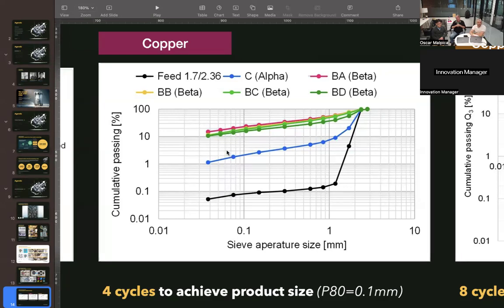The colored lines here represent 2 different test rigs. The blue line is our alpha test rig. It's an earlier test that we did with this material, showing about 2% cumulative passing at 0.1 millimeter. And then we show results from our beta apparatus on the same material, and you can see that it's pretty much a 10x improvement in breakage performance. So this is partly to give you an example of the comminution performance we get per cycle, but also to show the progression that we're getting with our generations of equipment. And the beta is not the end. We will continue to optimize and push these numbers up.